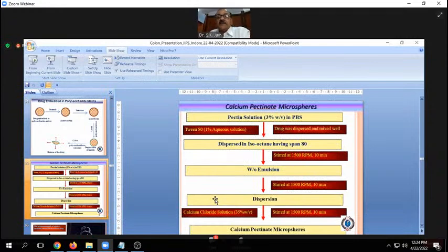I'll discuss only one of our research works, where we prepared calcium pectinate microspheres containing an anti-cancer drug. Here we prepared a 3% pectin solution in phosphate buffer saline, and added Tween 80, 1%, and the drug was dispersed and mixed well. Then this dispersion is dispersed in isooctane having Span 80, right? Stir at 1500 RPM for 10 minutes. We'll get the emulsion, say a water in oil emulsion, right? Again, further stir for 10 minutes, right?